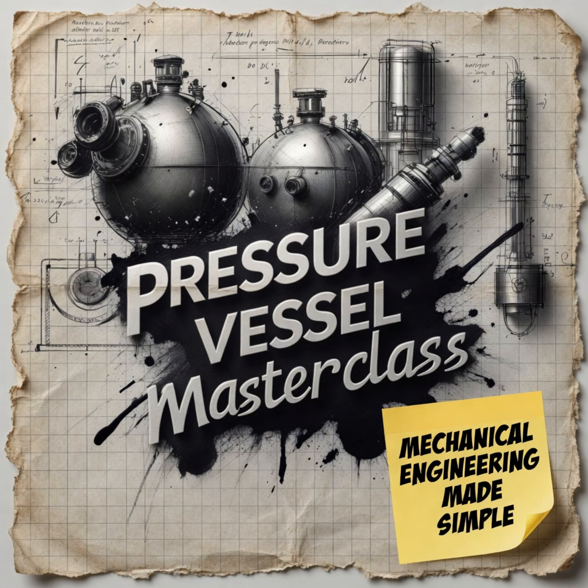People treat a hydro test signature like it's a blessing from the engineering gods. If a vessel passes hydro, the general consensus on the floor is that the vessel is invincible. That assumption is the proving fallacy, and it has caused countless disasters. Pumping a steel vessel full of water and holding it at pressure for 30 minutes at room temperature does not prove the vessel will resist cyclic thermal fatigue over 10 years of operation.